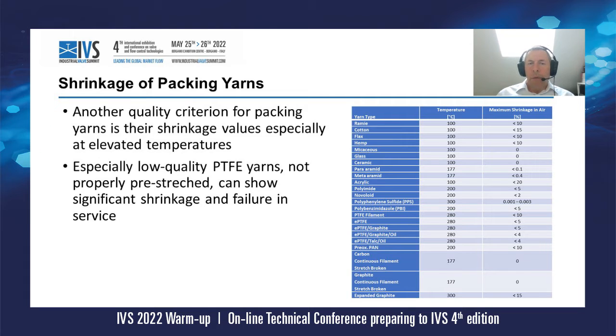Another quality criterion for packing yarns is the shrinkage value, especially at elevated temperatures. A table has also been created with the help of manufacturers to show maximum shrinkage values in air at elevated temperatures. Especially, for example, low quality PTFE yarns not properly pre-stretched can show significant shrinkage and failure in service due to extrusion and related high gland pressure losses, but also with other materials which show high shrinkage, problems can occur and the service life will be shortened.